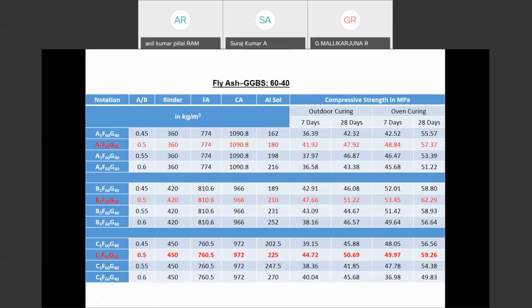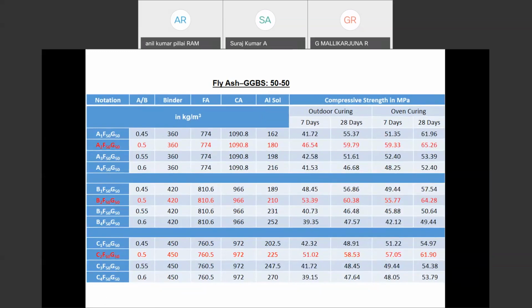And next one is 50-50. Here, 50% fly ash and 50% GGBS content. Here for 360 kg per meter cube, we approximately produced 59 MPa strength after 28 days without any oven curing, so we achieved our required strength, and we produced strengths from 20 MPa to 60 MPa by using these different combinations of fly ash and GGBS.